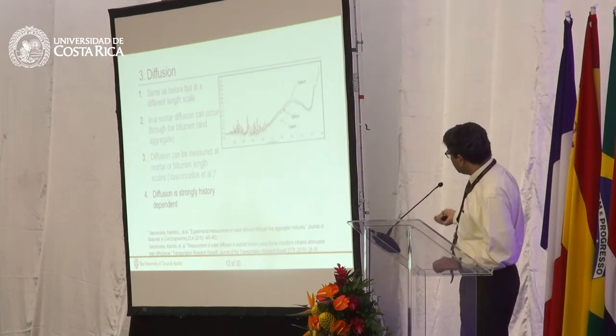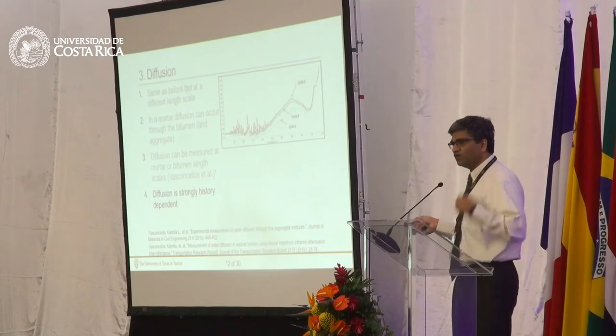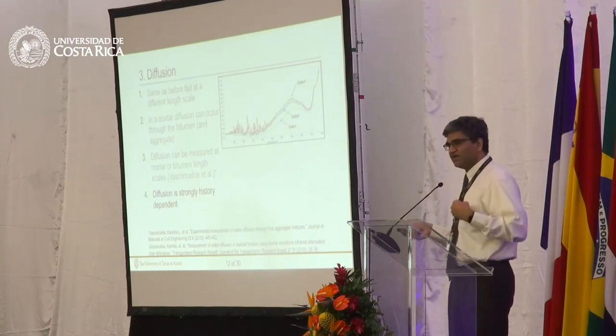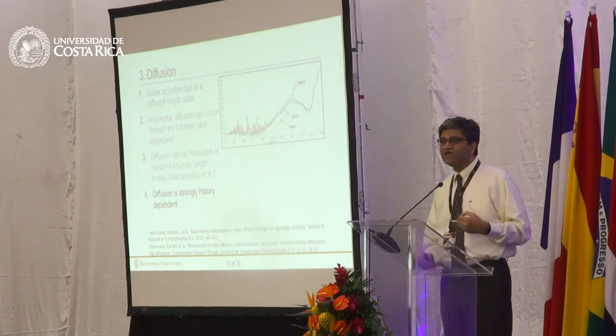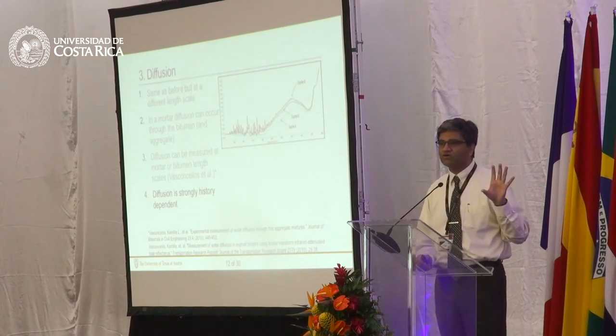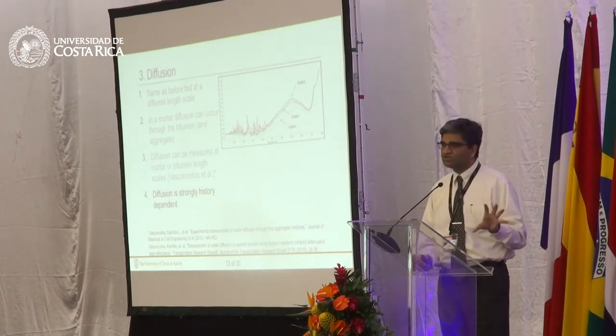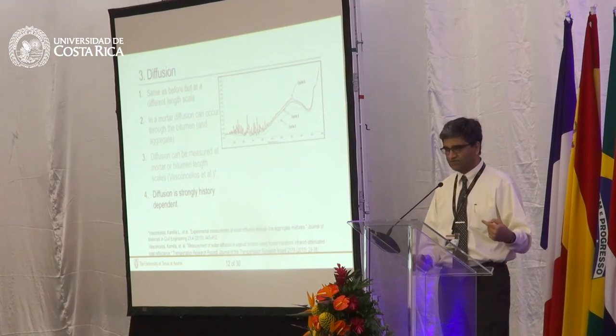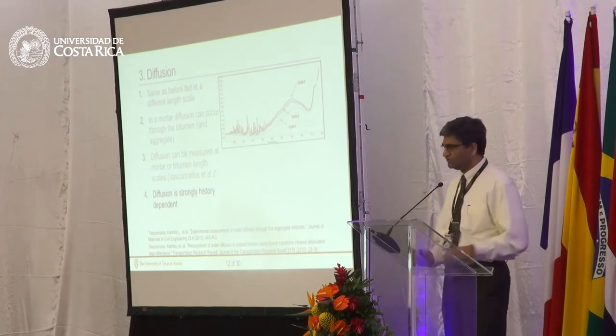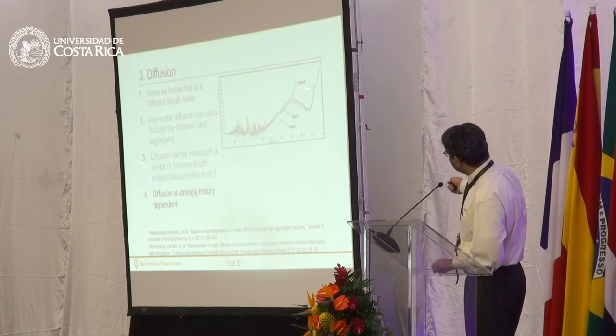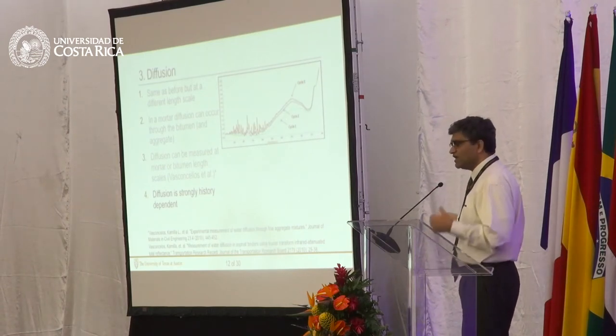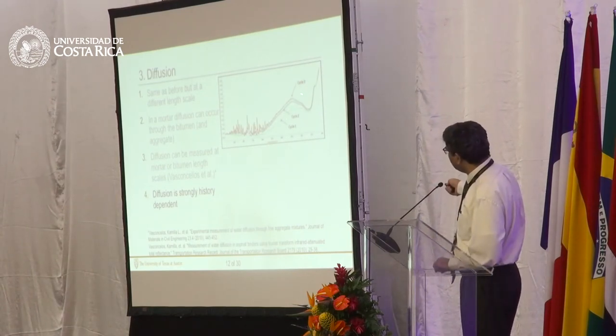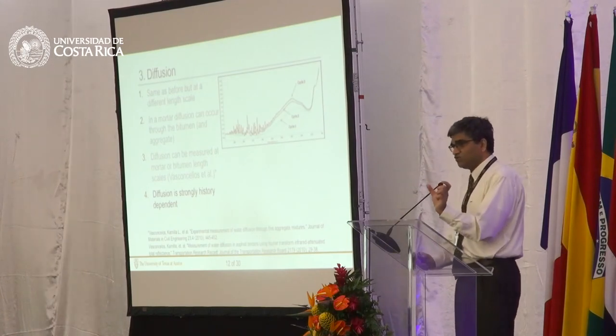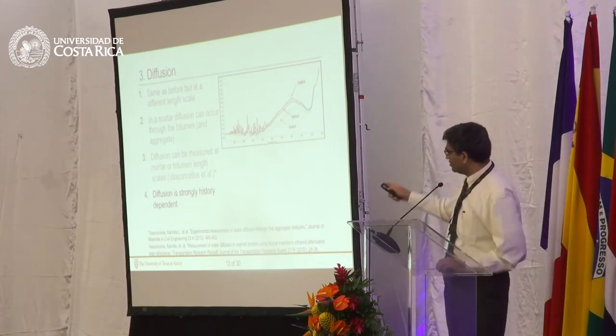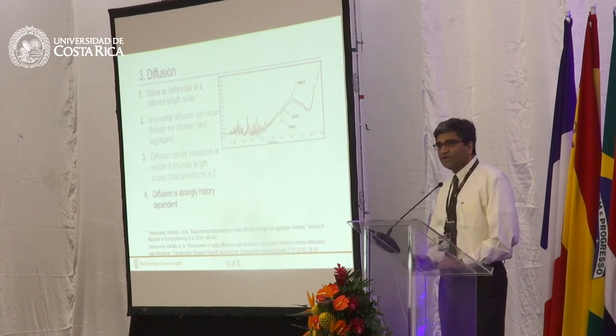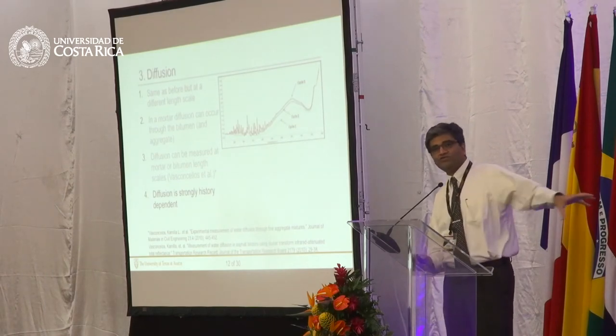That was this other study where we looked at diffusion, where we cycled water. We exposed the material to water and then dried it, exposed it, dried it. And what we found was, every time bitumen was exposed to water, it changed. It changed structurally so that the next time it was exposed to water, the diffusion was much faster. So what you see here is cycle one, cycle two, cycle three. You see the effect of these cycles. In the same amount of time, you would get more and more water for the same period of exposure, meaning what happened before. So even though the sun comes out tomorrow morning, it's not like the binder would go back to its original state.